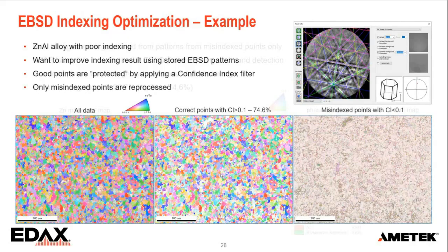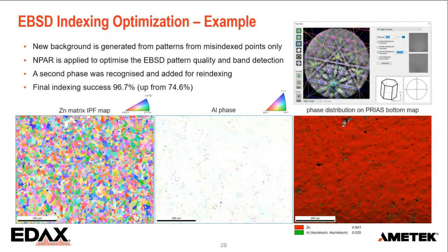And when I do that, here on the left you see the result. Now the result is almost 97%. So it's more than 22% improved over the initial indexing. And actually, there was a secondary phase in there that I also had missed initially. So saving the patterns and doing this offline really allows you to maximize the analysis results.